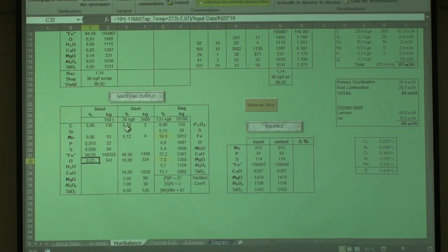Okay. The dust is a standard analysis. Yeah. And here the amount of dust, we have seen that for standard conventional EAF, modern UHP, it is in the range of 18 to 22. Yeah? Of course, in local conditions, if you have dirty scrap, you may have more dust than this amount. Yeah? Okay, let's go back to the slag.